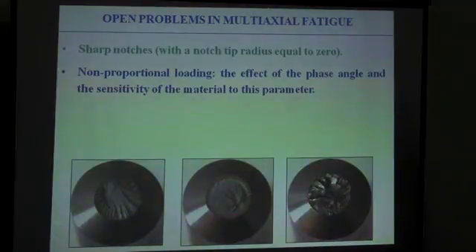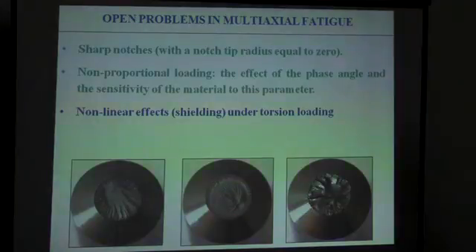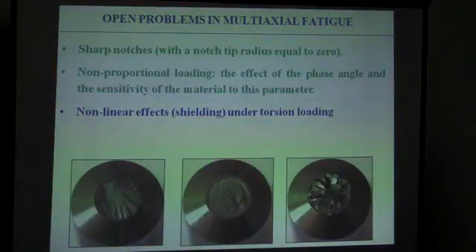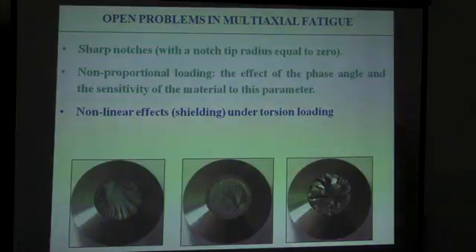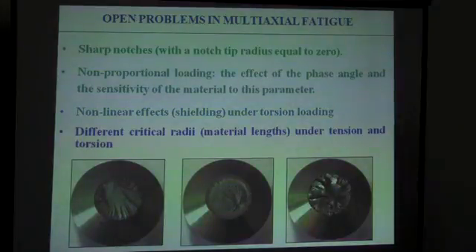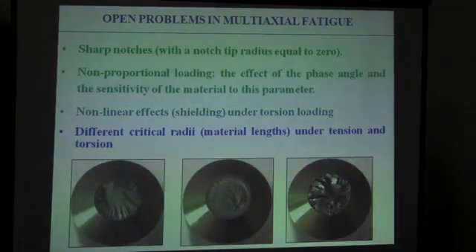Another important aspect is how to take into account the non-proportionality for this kind of sharp notches, and for this kind of geometries, always as discussed by Professor Tanaka, we have nonlinear effects, shielding effect in particular under torsion loading, and when we have a nominal load ratio equal to R = -1.